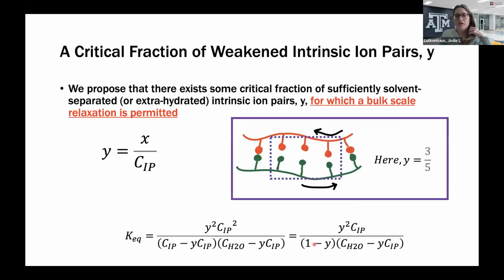Okay. Now, we propose that there exists some critical fraction of sufficiently solvent separated or extra hydrated intrinsic ion pairs, Y, for which a bulk scale relaxation is permitted, such as a glass transition or that relaxation time we saw in dynamic mechanical analysis. So here is a picture where I'm trying to draw that, where these are still correlated, but they're slightly separated because there's been additional water molecules input into them. So we may say Y is 3/5, and maybe that's enough to allow some relaxation that we might be able to observe.